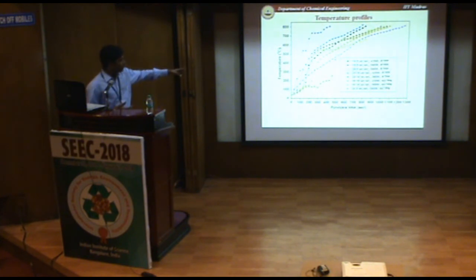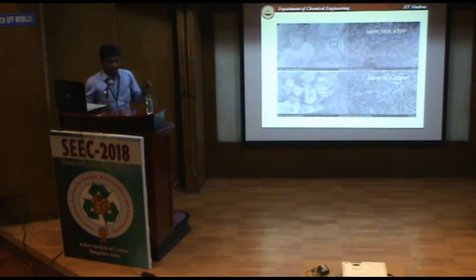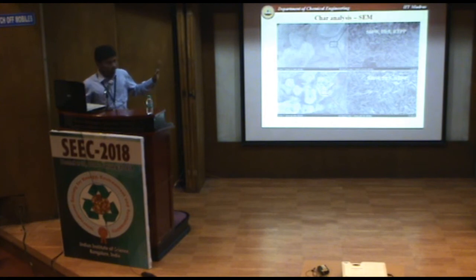And you can see these are the temperature profiles. The longest duration is because of the low amount of susceptor, and the shortest time is because of the high amount of susceptor. Susceptor, in the sense, is something which can absorb microwaves effectively. And I'll start the char analysis with SEM. These are a few snaps that I'm showing here, and the first diagram is taken at 30 micrometers. And of course, I have to say something: before pyrolysis, the iron was mixed with coal, and we separated the iron, because the iron particle size is quite different from the coal particle size.